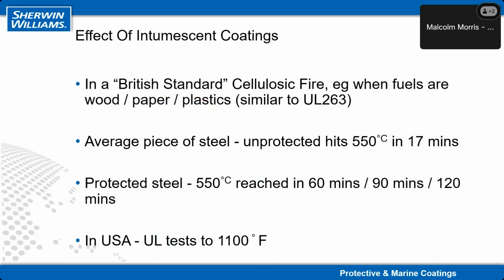So we have a series of what we call standard fires. There are British standards, European standards, American standards, many different standards which will effectively create a standard fire which we test against. So in a British standard fire situation, an average piece of unprotected steel hits that critical temperature, around 550 degrees C, in about 15 to 20 minutes, or typically 17 minutes. It depends on the actual size of the steel, we'll see in a minute. But what we're aiming to do is increase that 15 to 20 minutes to 60 minutes or 90 minutes or even 2 hours. And that's why people talk about 60 minutes, 90 minutes, 2 hours fire protection. It is that extended period for which we are aiming to preserve the integrity of that steel structure.